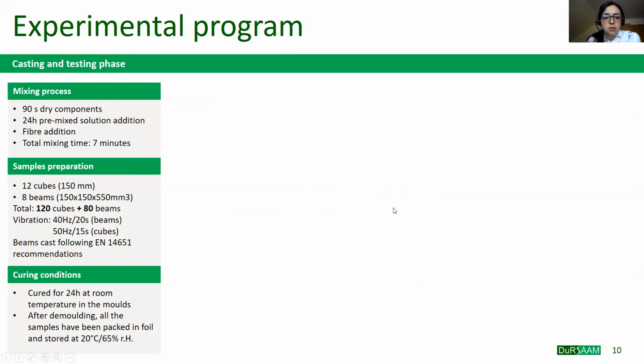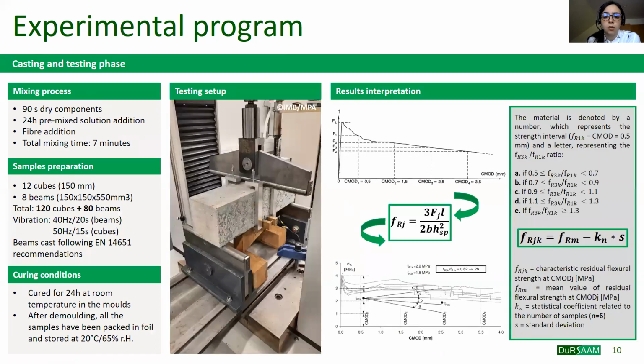During the casting phase, all the 10 mixes were prepared following the same mixing procedure and applying the same curing conditions. A total of 120 cubes and 80 beams were cast. 3 cubes after 1, 7, 14, and 28 days were tested to evaluate the compressive strength development over time, and 3-point bending tests were performed on 6 beams for each mix, following the recommendation of the fib Model Code 2010 and the European Standard EN 14651.